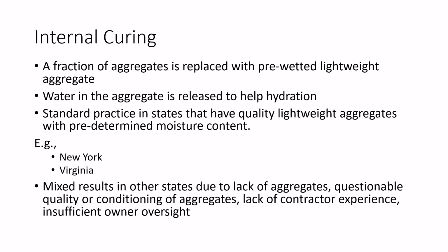So for external curing, the key is to start right away, but there is a new, innovative way of curing concrete called internal curing. Essentially, you replace a fraction of your aggregate with a pre-wetted lightweight aggregate. The water in that aggregate is released over time to help hydration. So instead of just hydrating the surface of the concrete, you are essentially hydrating from the inside out, so internally.